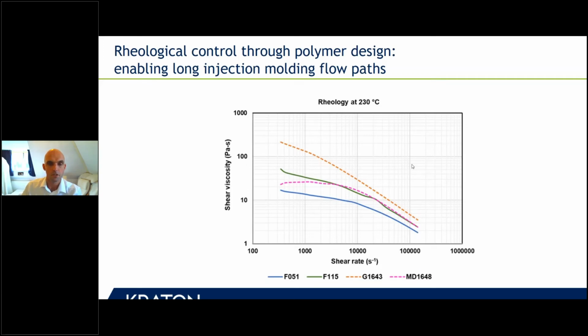contribute the other part. So this is all about the rheology of the HSBC we're using, and these are two chemically comparable HSBCs in the dotted line. So G1643 is an ERS grade Kraton, and you see the curve here in orange. And if you redesign that polymer, and that's a combination of styrene block size, molecular weight, etc., you can significantly reduce the shear viscosity. So depending on shear, you get a much better flow. And this is of course helping injection molding in this region, which is the typical shear rate in injection molding.